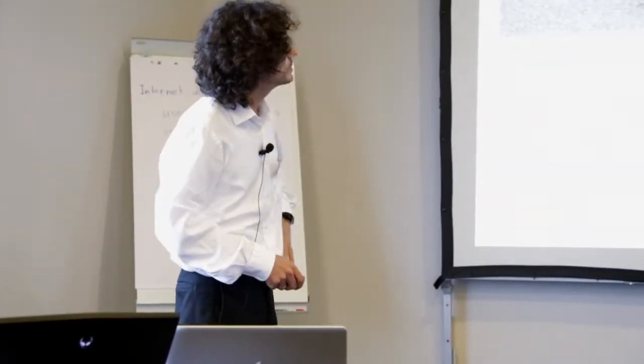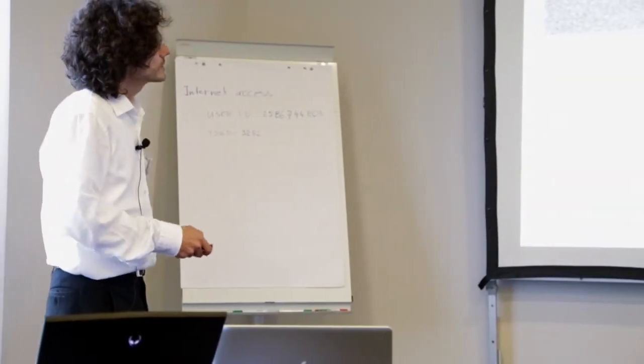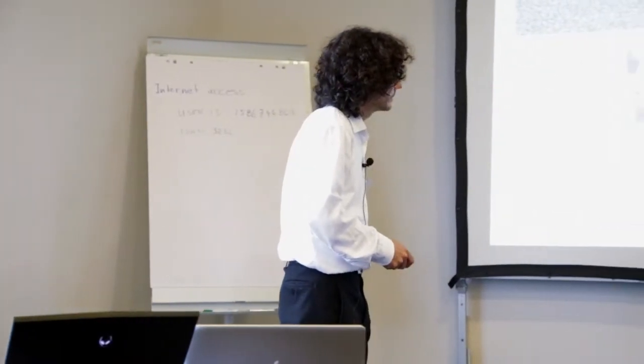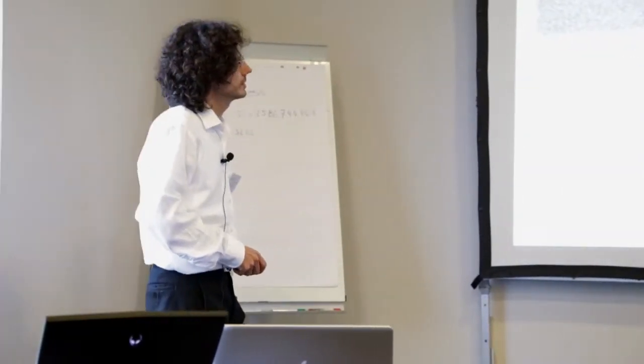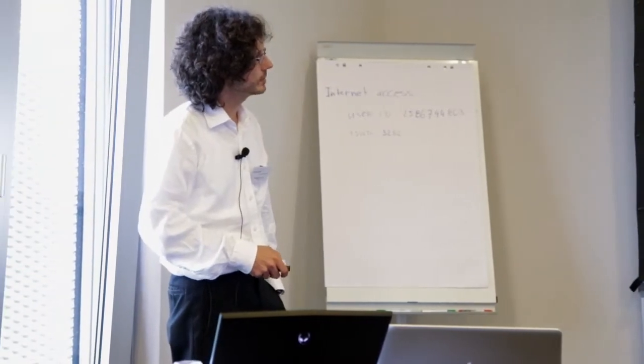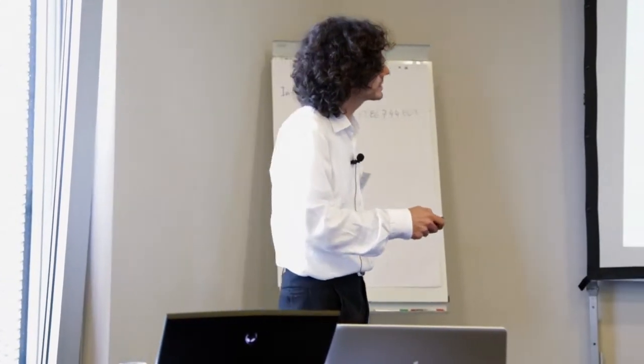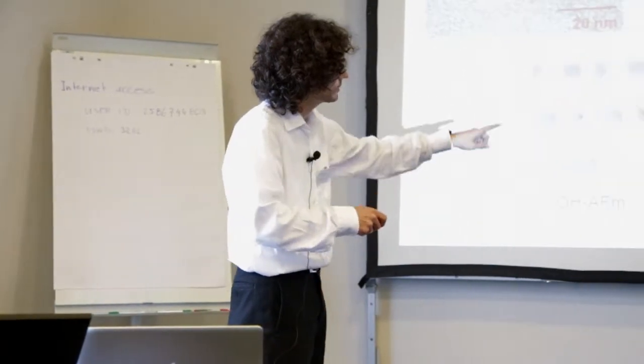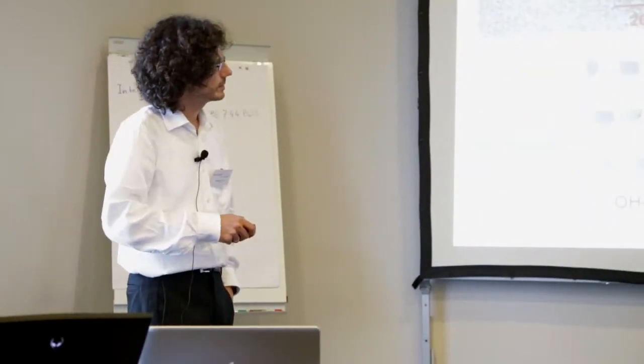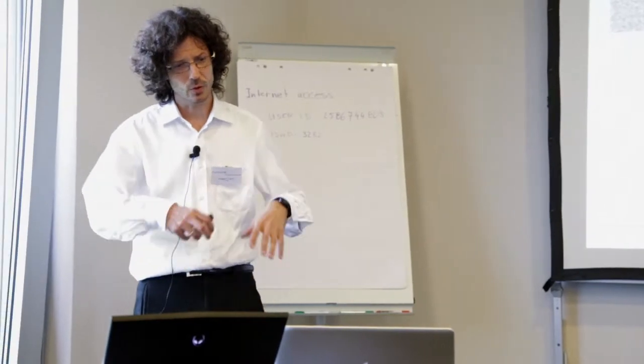So let's move forward. We also can determine that there is a remainder of the in-plane reflections from this phase, therefore we really can trust this kind of LDH model with intercalated polymers. And with the kind of layer spacing that we get, these values actually will be revised on one of the later slides. We move towards the idea of a coiled conformation of the side chains in this interlayer.